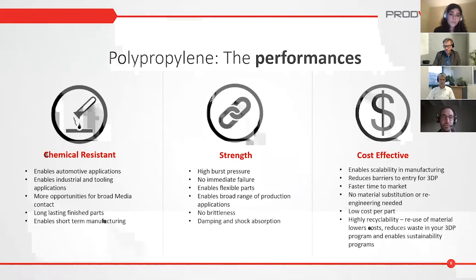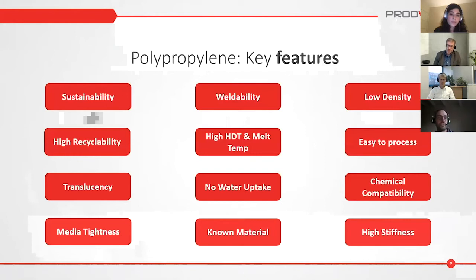Moving on to the next slide, I can also tell you a bit more about the key features of polypropylene. Starting from the upper left corner, sustainability. First of all, since PP is so widely used, recycling processes do exist for such a material, which is often not the case for other 3D printing materials, because often they are not so widely used. With PP, you can recycle printed parts much more easily. Second, and it has to do with the high recyclability of the material, the refresh rate in the printer is quite high, so you can reuse the powder, which leads to less waste during the printing process.